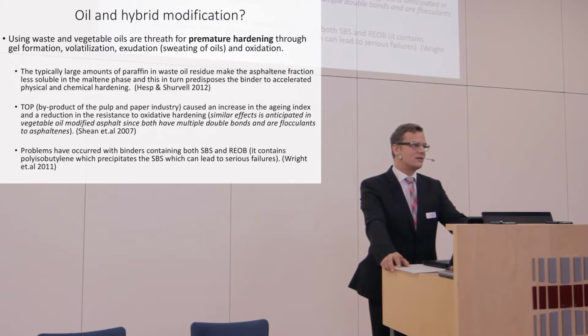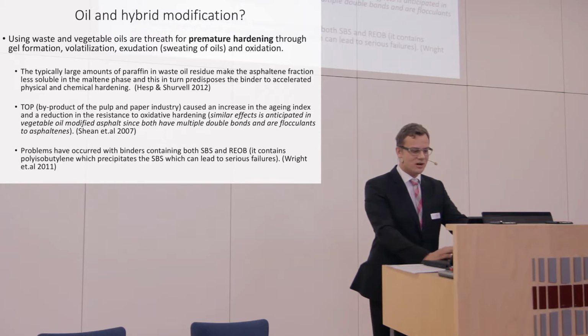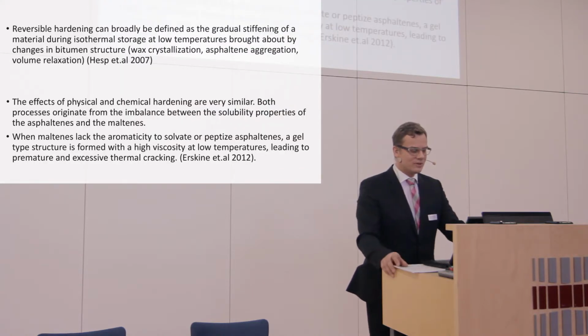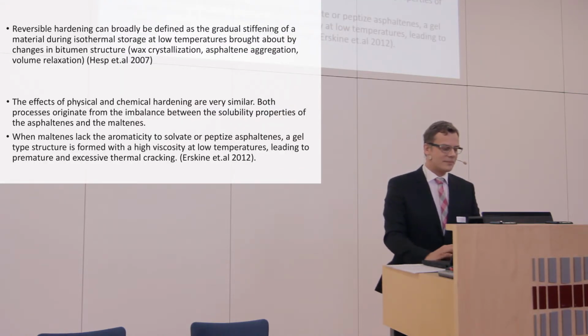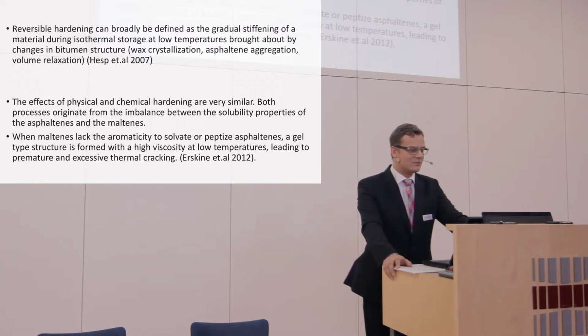So what does all of this mean? What is this premature hardening, or this physical or chemical hardening we are warned about? Hesp et al. 2007 stated that reversible hardening can broadly be defined as a gradual stiffening of a material during isothermal storage at low temperatures, brought about by changes in the bitumen structure - that is, wax crystallization, asphaltene aggregation, and volume relaxation.